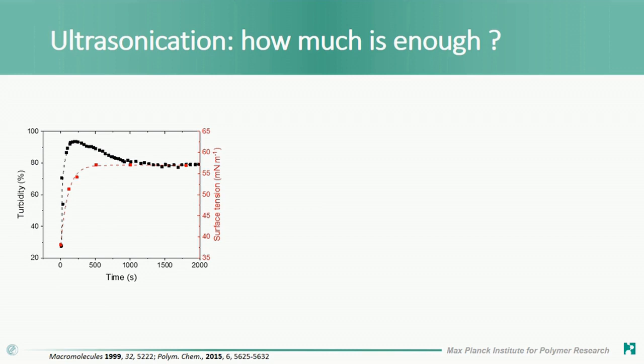And to measure the size of the droplet by light scattering, for example, you need to dilute your sample. And by diluting your sample, because it's too concentrated for light scattering when we do miniemulsion, you're changing the position of the equilibrium, and it could change the size. So directly measuring light scattering of a dilute solution, the size that you measure is not exactly what is in the emulsion.